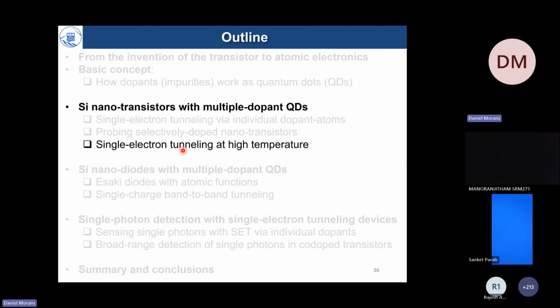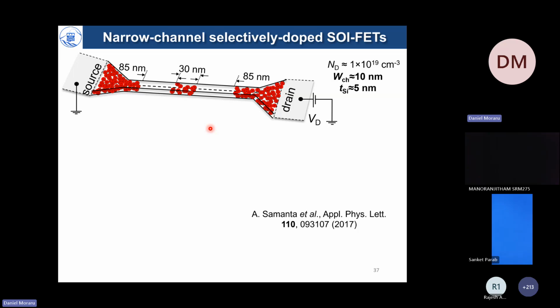So now I'd like to move to the high temperature operation of these devices. In this kind of devices, we aimed ideally for the high temperature operation. So we spent the next few years, until 2017, let's say, to optimize our devices in a few aspects. One was to make the pocket very, very small. So we designed it to be just 30 nanometers with a slightly bigger barrier. So even if we have a side diffusion, we can still keep these barriers undoped.